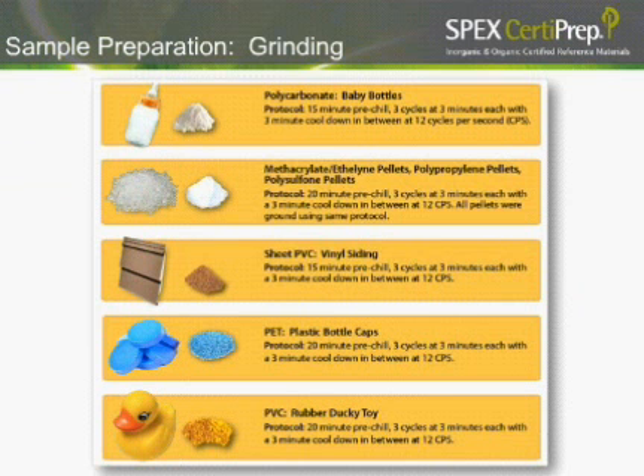But asking our company, Spex Sample Prep, for some tips and tricks about how you grind the different polymers, they went through their experiences with their customers, and they came up with a snapshot of some different polymers and how you could possibly treat them. You have something like a polycarbonate, which actually shatters pretty quickly, so it has a little bit less of a pre-cooling cycle. Then you go down to a PVC, and that particular type of plastic with additives could be challenging or problematic to grind, so that has a little bit more of a pre-cooling cycle. But this is a nice little guide to at least start you in the right direction of where you want to be with your grinding.